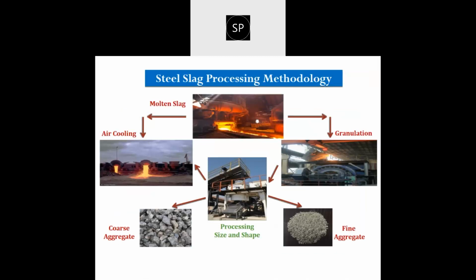Now another method to process the slag is its granulation. In this particular process, the molten slag is directly poured into the granulator, where through the water quenching process, the slag can be converted into sand size particles, and it is called granulated slag. And normally this type of process is employed for blast furnace slag, the slag which is generated inside the blast furnace during the production of pig iron from iron ore. This blast furnace slag can be utilized in the form of a fine aggregate, and if it is further ground, then it can be utilized as ground granulated blast furnace slag, which, due to high hydraulic activity, can be utilized as a direct replacement of cement in pavement quality concrete.